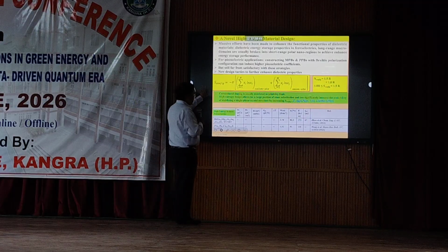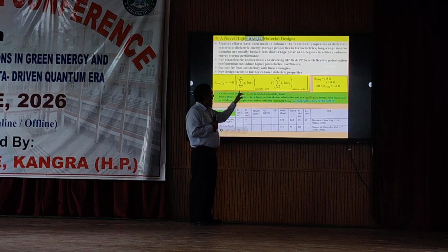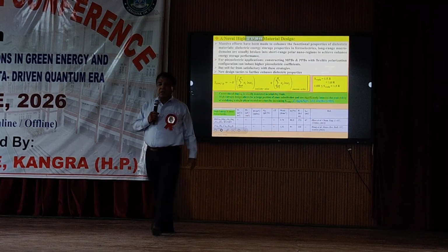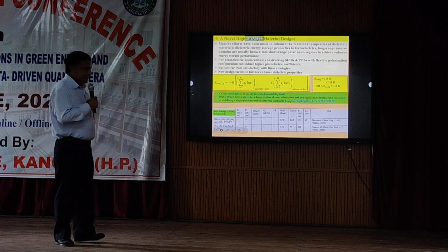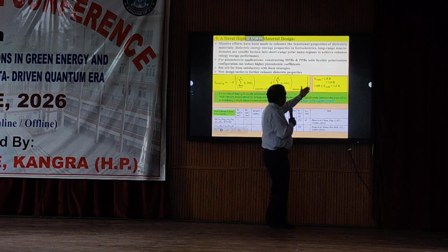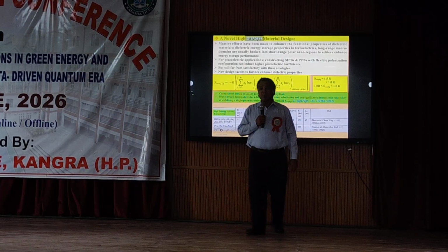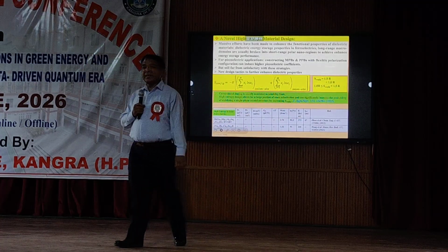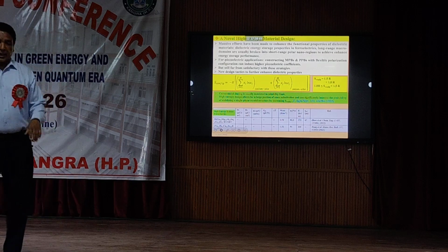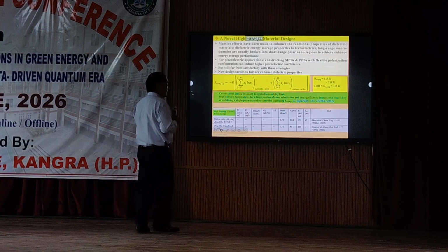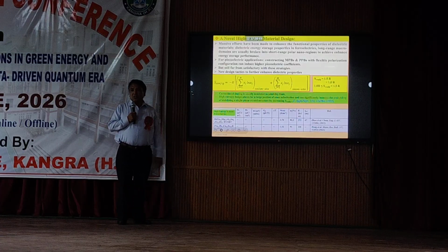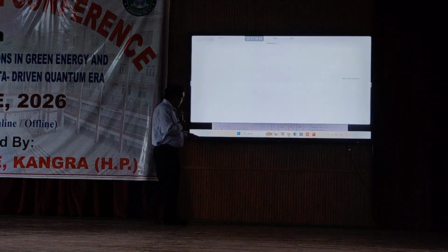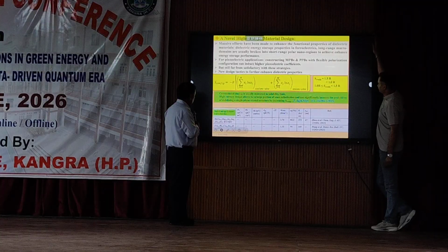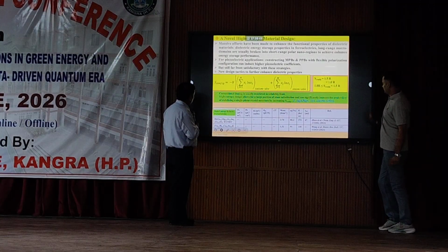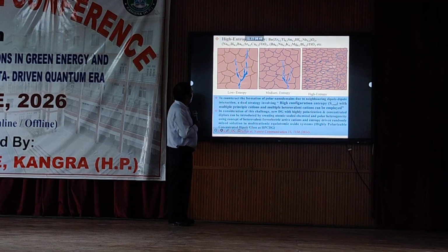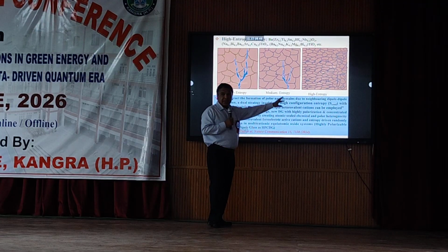So high entropy is defined by this kind of formula, where R is the ideal gas constant, Xi, Xj are the molar concentrations of elements at the cation and anion side, or A or B side. So when this entropy is greater than 1.5 R, we call that a high entropy material. If less than 1 R, then low entropy material, and in between 1 and 1.5 R, then medium entropy material. Why are these materials important? Because entropy is the crucial factor to have enhanced energy storage density.